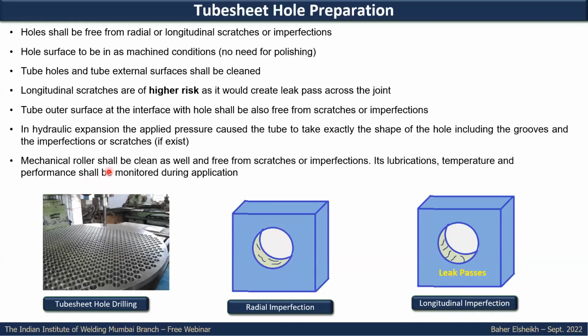When you're applying the two different techniques normally used in the expansion, whether mechanical rolling or hydraulic expansion, as we'll see on the next slide, the hydraulic expansion will force the tube to take exactly the shape of the tube sheet hole, including any imperfections or scratches left in the tube hole. That's why it is very crucial to have it well machined to avoid such impact on the tubes, which might lead to cracking in the tube in future, or to a leak path between the tube side and shell side.